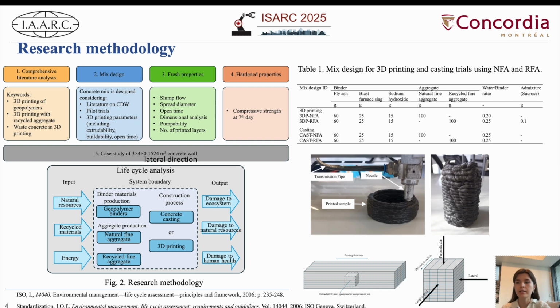After that, we conducted compressive strength tests on the 7th day of the carbonation curing. These tests were performed in three orientations, XYZ, to reflect the anisotropic behavior of 3D printed concrete, and it was in accordance with standard procedure. Finally, we carried out a life cycle assessment to compare the environmental impacts of 3D printed concrete with traditional casting.